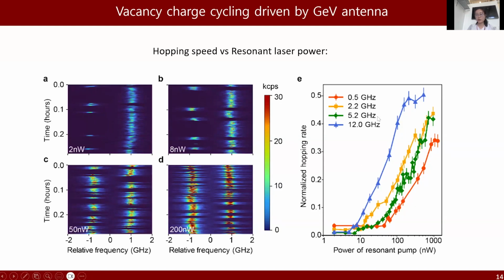The right figure shows a correlation between this threshold laser power and the GeV ZPL splitting magnitude. This makes sense because the splitting magnitude simply indicates the distance between the vacancy and the GeV. A larger ZPL splitting magnitude simply means that the vacancy is closer to the GeV, so that lower power is required to drive such charge cycling.